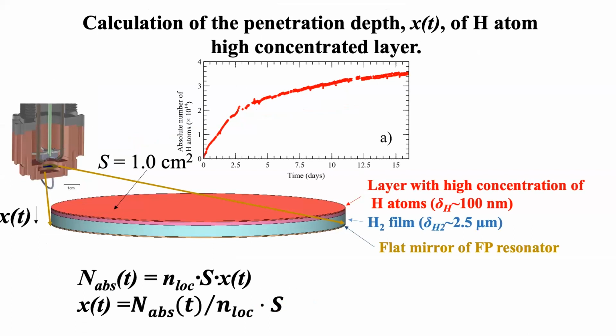First, we know about our sample that the total number will equal the local concentration multiplied by volume. The local concentration in this second stage doesn't change; we know exactly how it is. We know the surface of our sample, our flat mirror where we create the sample.